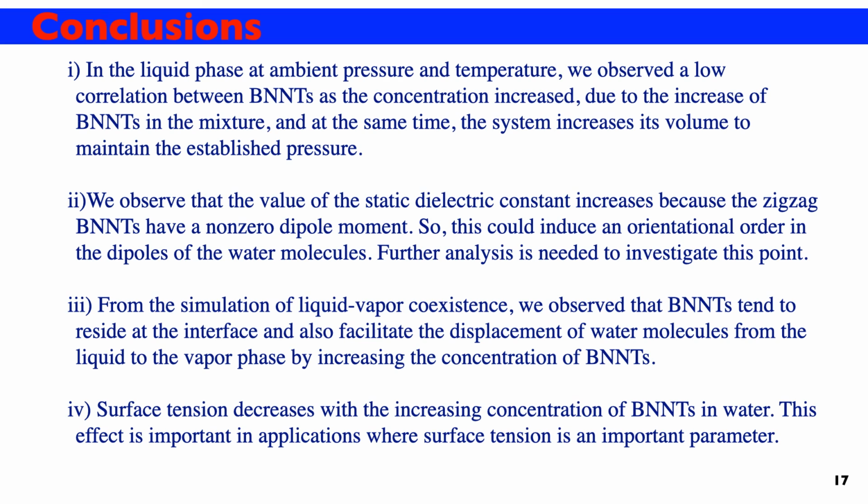We observe that the value of the static dielectric constant increases because the zigzag nanotubes have a non-zero dipole moment, and the interaction between water molecules is of dipole-dipole type. So this could induce an orientation order in the dipoles of the water molecules. Further analysis is needed to investigate this point.